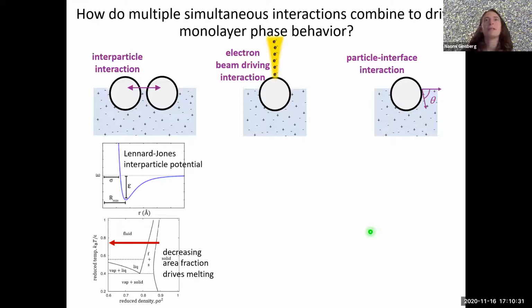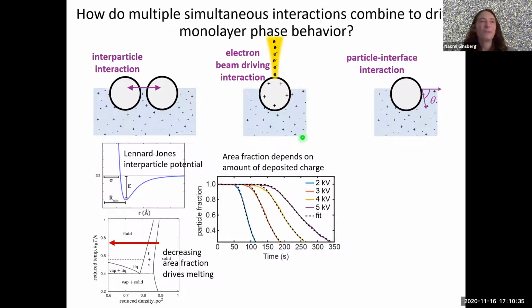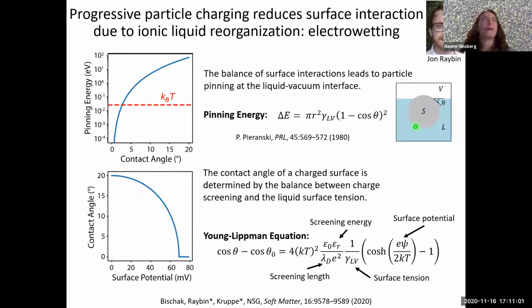Okay, so considering the electron beam driving interaction, what we primarily learned is that the area fraction depends on the amount of deposited charge. And the last ingredient we have to include in a model to describe the progressive disappearance of the particles from the interface is, of course, the surface interactions themselves. If there weren't any surface interactions, we clearly wouldn't be able to stabilize particles at the interface in the first place. Okay, so in general, the equilibrium configuration of an uncharged particle relative to a fluid-fluid interface like this one can be determined by comparing the surface interactions of the particle with each of the fluids to the fluid-fluid interaction that would occur in the absence of the particle itself.